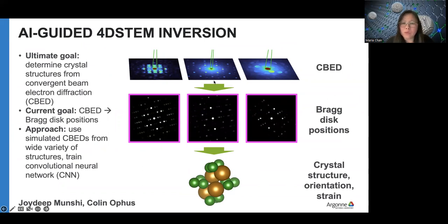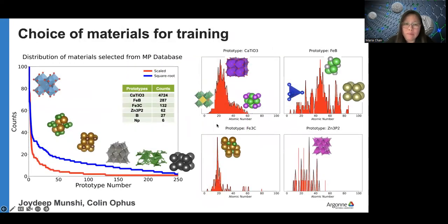So the approach we used was to simulate a very large number of CBED images, and then train a convolutional neural network in order to carry out the mapping between the CBED image and the Bragg positions. So we need one model to work for everything. So we need to have a large selection of materials, and we did that using the Materials Project database. But we don't want too many duplicates or similar structures, so we actually use the crystal structure prototypes from AFLOWLIB. In addition, we also try to balance out the atomic mass distribution because they affect the scattering of the electron beam. So we want to represent different atomic numbers.